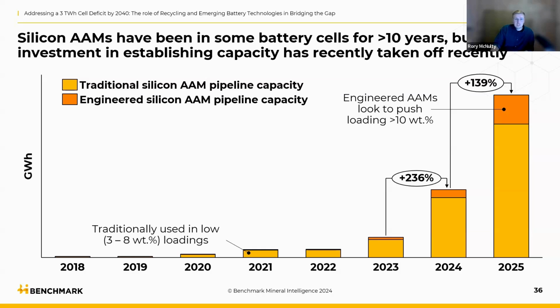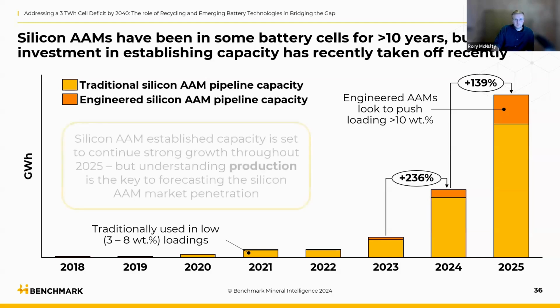However, we've also got these engineered silicon anode active materials, which are using novel nanostructures and techniques in order to contain and utilize that swelling, pushing silicon loading anywhere from 10 weight% all the way up to silicon dominant anodes that can use sort of 80 to 100 weight% silicon.